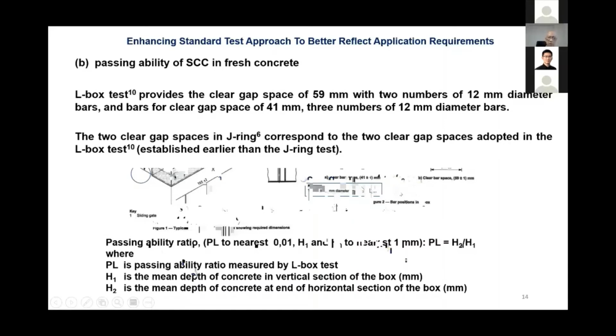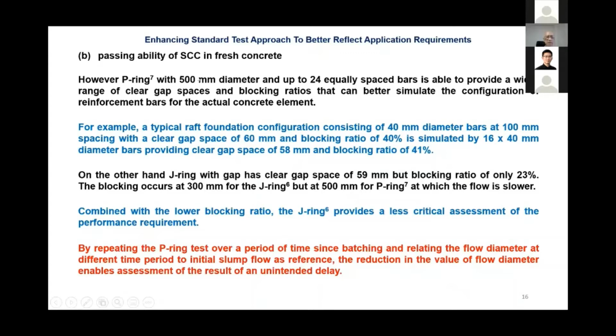Table 3 is what we have turned up to produce later on to show what happened. With a P ring with 500 mm diameter, we have 24 equally spaced bars. We can provide different combinations of clear spacing as well as blocking ratio. Let me take an example of a very common one, raft foundation, 40 mm bars at 100 mm centers. So you can see the clear space between the bars is only 60 mm, and the blocking ratio out of the 100, 40% is blocked.